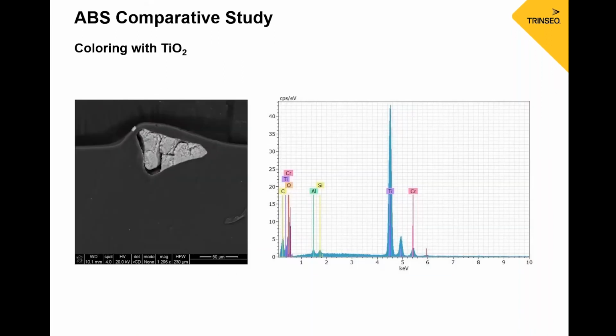Another risk with highly loading TiO2 is causing agglomerations of the colorant. And this was an example where surface defects were observed, and we investigated that and found the defect was resulting from agglomeration of the TiO2 particles in the product. So if you're able to reduce that level of TiO2, you reduce your risk of agglomeration and surface defects also.